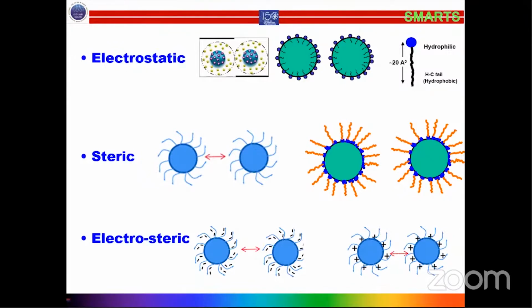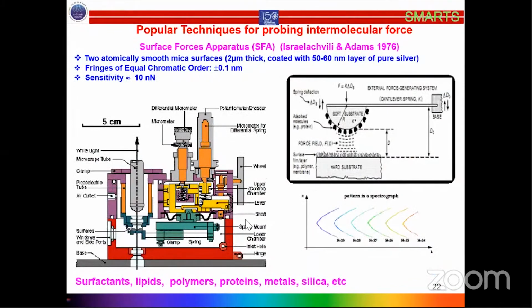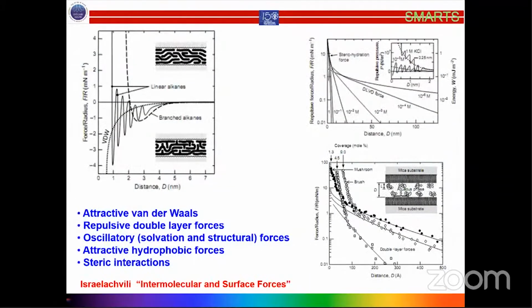Now the problem is, how do you probe this interaction? One of the elegant techniques, developed in the 70s, is the surface force apparatus, where you can probe the interaction forces between two macroscopic surfaces, for example two mica surfaces, where you can control the spacing within nanometers, even at the angstrom level in the most recent ones, and look at the interaction forces. This simple Hooke's law is applied here to get the forces that are measured. So this is a beautiful facility when it comes to macroscopic surfaces.